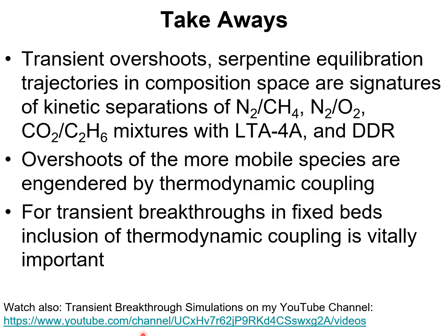For all three cases, we established that transient overshoots and serpentine equilibration trajectories in composition space are signatures of kinetic separations.